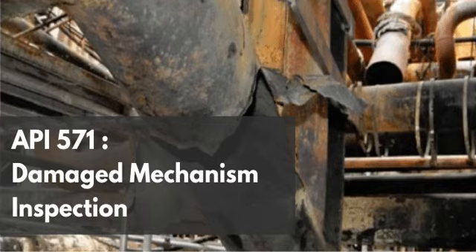But the API text explicitly defines the actual kinetic danger zone as exposure to temperatures in the 600 degrees Fahrenheit to 1,000 degrees Fahrenheit range. Or 315 degrees Celsius to 540 degrees Celsius. Correct. If your susceptible metal, whether it's a 440 stainless tray, a 2205 duplex pipe, or a 347 stainless weld with 8% ferrite, is operating anywhere within that 600 to 1,000 degree Fahrenheit band, the clock is ticking. The alpha prime precipitates are forming.